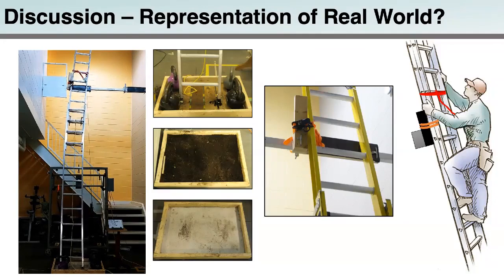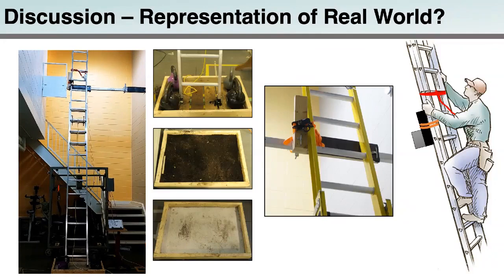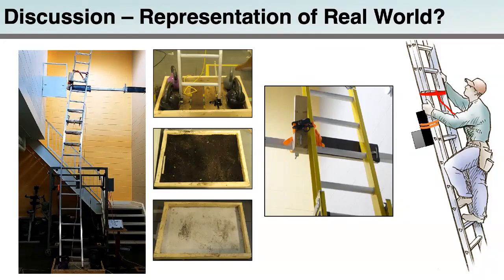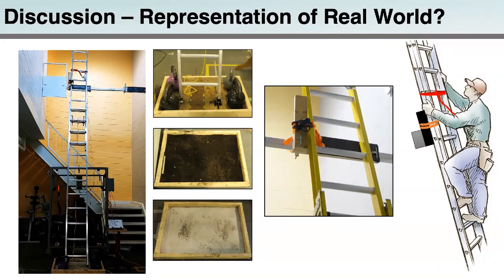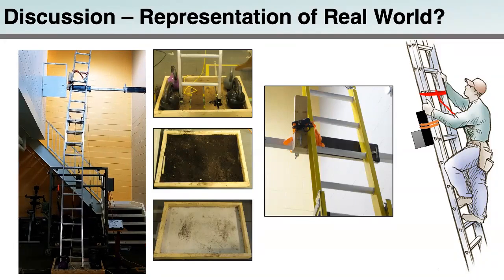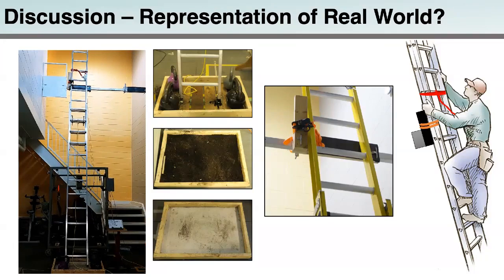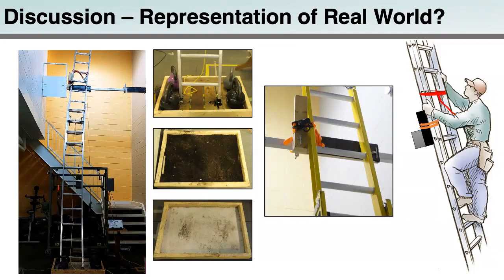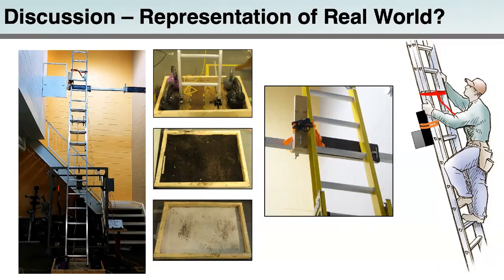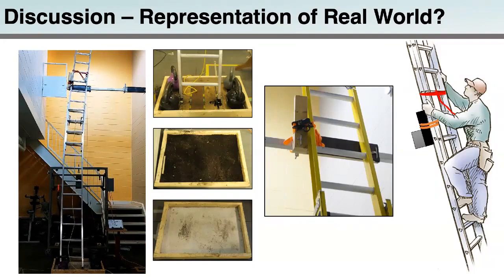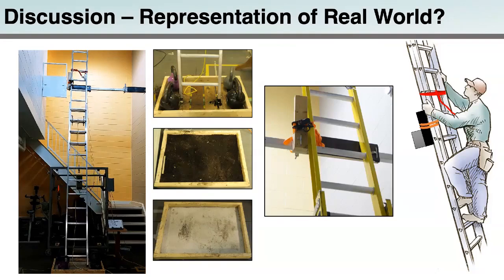Thus, the conditions that produce the greatest amount of deformation may not be representative of a real fall, but all conditions regardless pass, and results from this investigation indicate that even in these extreme directions, the ladder didn't fail during a single loading event. And the failures that we did see were likely linked to the cumulative drop tests that were being completed on the ladders.